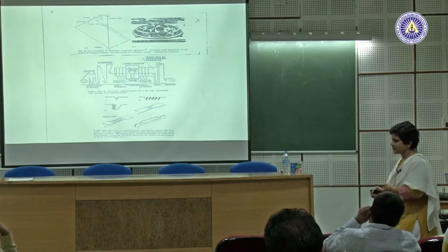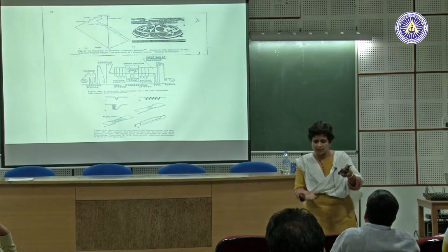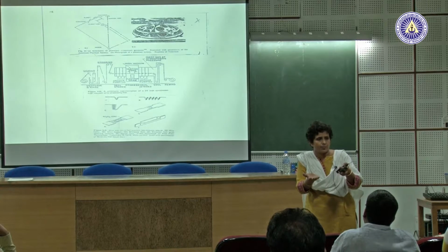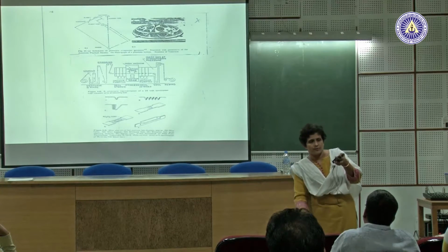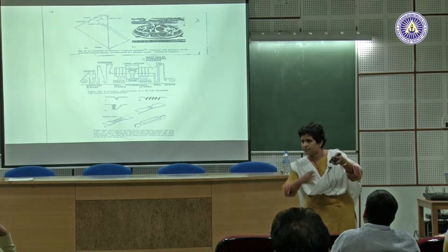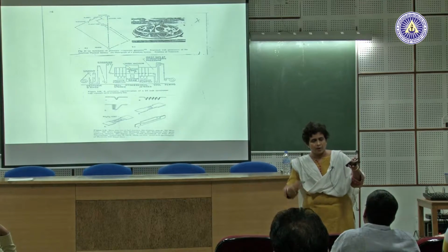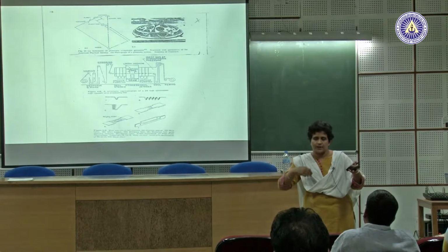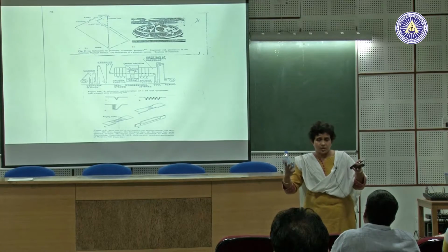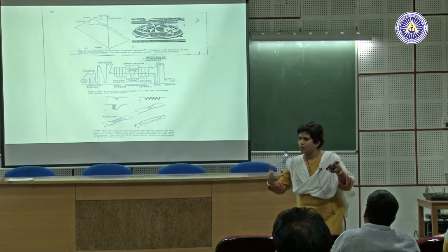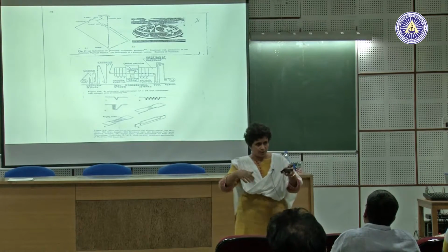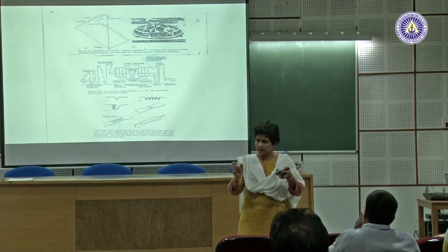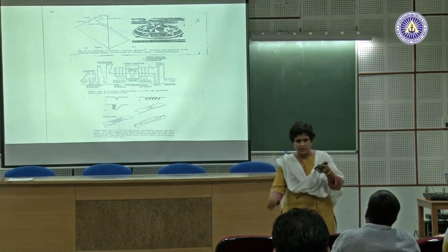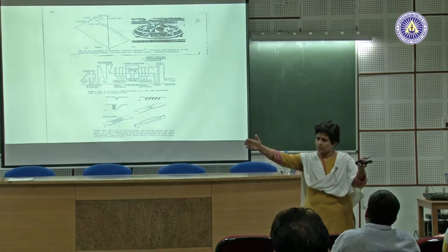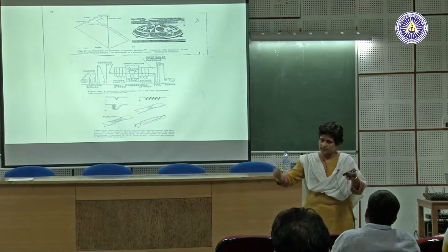One thing you can immediately see, if you have a lot of non-uniformity, the closer you bring the source to the substrate, the more non-uniformity there will be. So the farther you take the source from the substrate, the more uniform it becomes. If you want very good uniformity, and when you are in production, you want deposition taking place, throughput should be high. You want many substrates, or whatever you want to deposit on, to go through in a shorter time, right. So one option would be to keep the source very far off and then deposit on something.